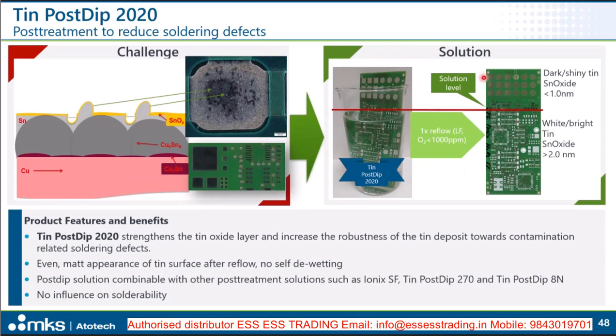The simple test that we did here was just to immerse the tin plated panel in the tin post-dip solution, then do the reflow aging, and what we see afterwards is that in the areas where we applied the post-treatment, we have a nice white clean tin layer, while on the areas which were exposed to air and were not immersed in the tin post-dip 2020, we have a dark appearance. So this is really a clear indication that the increase of the oxide layer can help to prevent these defects.